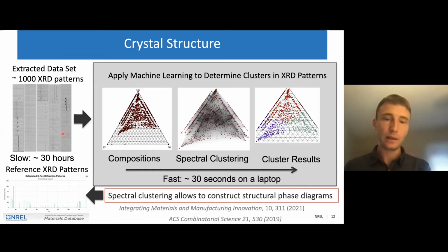We have tested and optimized a particular machine learning algorithm that enables us to convolute the composition measured for each of these X-ray diffraction patterns with the similarity of the X-ray diffraction pattern itself to perform spectral clustering. So we have this custom distance metric in the composition and structural space that we use to perform sample clustering and look at the similarity of different samples that we made, both in terms of proximity of their composition, as well as the similarity of diffraction peaks that they have. And running such analysis on this particular data set results in something like this.